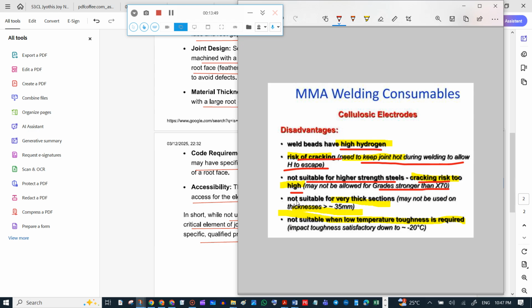Not suitable for very thick sections. So we are using it only for the root gap because of this high hydrogen content. Cracking problem is there. Not suitable where low temperature toughness is required. So we are using it only in the root pass. Otherwise, the impact toughness will be satisfactory down to minus 20 degrees.